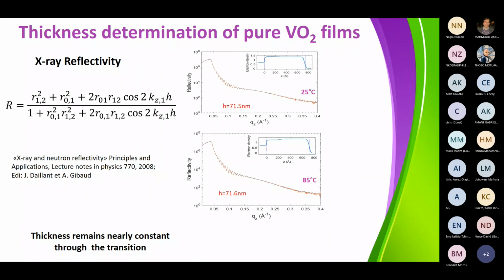Okay. But what we learned in doing those reflectivity measurements at low and high temperature was that the film thickness was not evolving much. So you could keep it almost constant. You see it's 71.5 at 25 degrees, and it's 71.6 at 85. No change at all, almost. So it means that although you have a phase transition, in this case we don't see much of a difference between the two thicknesses at low and high temperature. So that was a story about the determination of the thickness of the film. And that's a very important story, because then in ellipsometric measurements, it means that we can keep the thickness constant. And you will see that the thickness is a very important parameter.